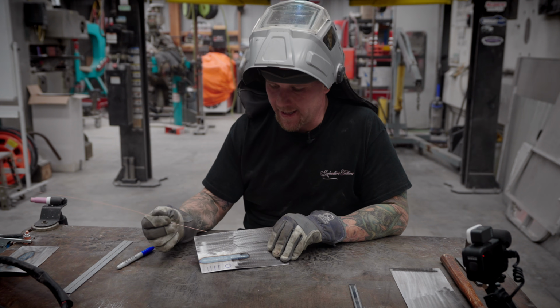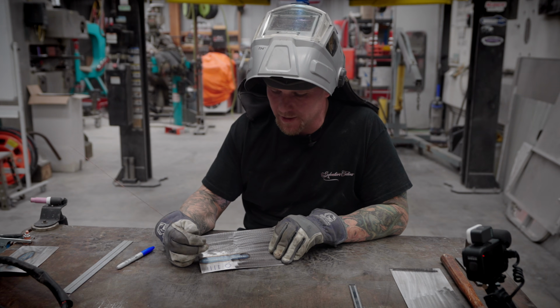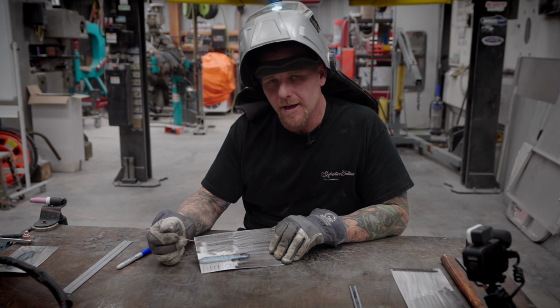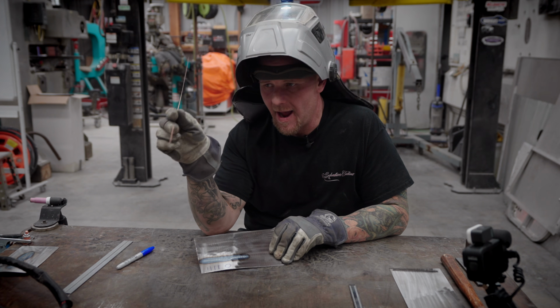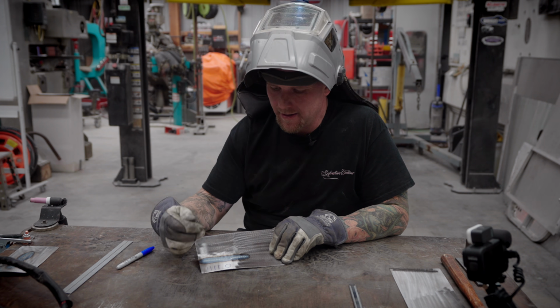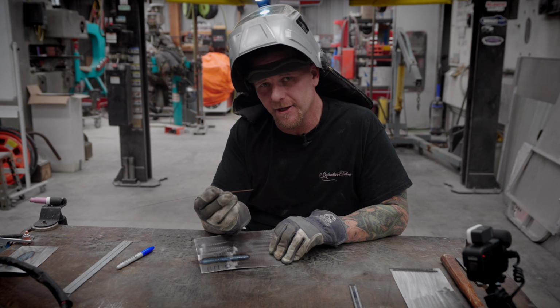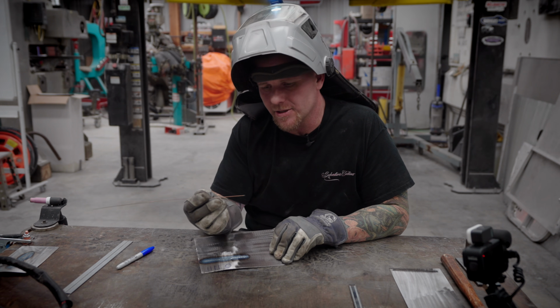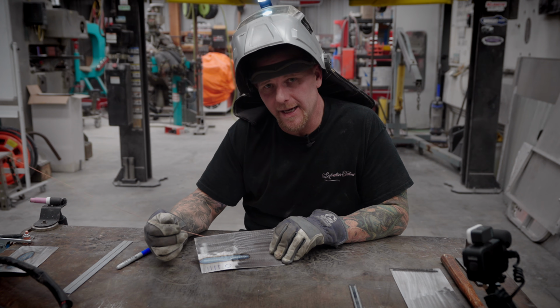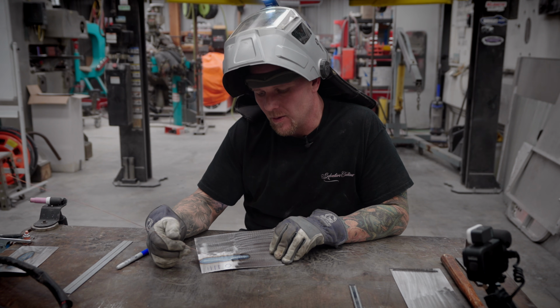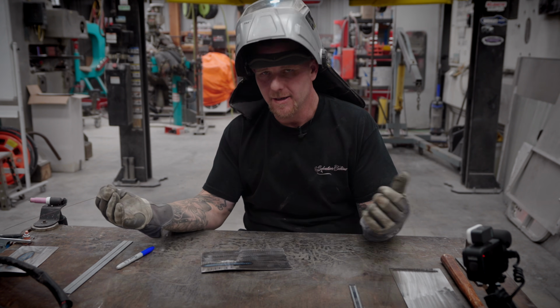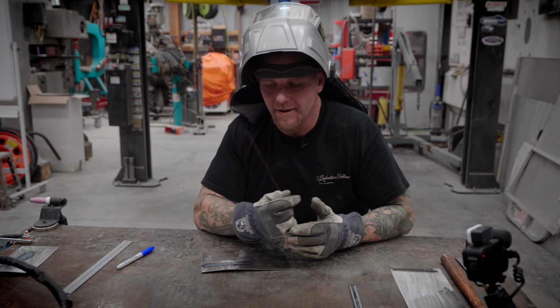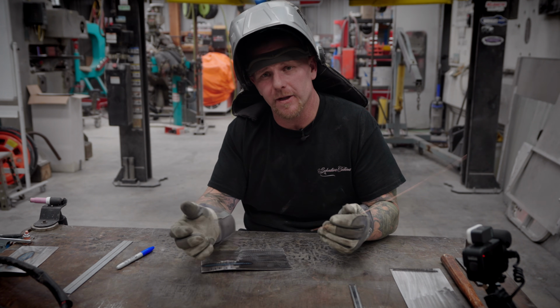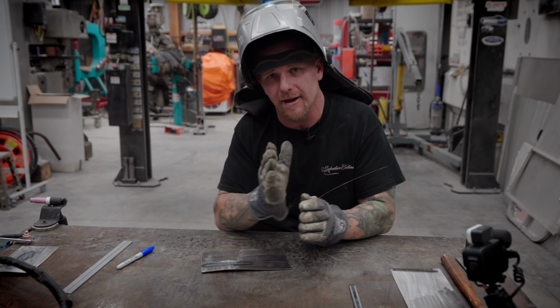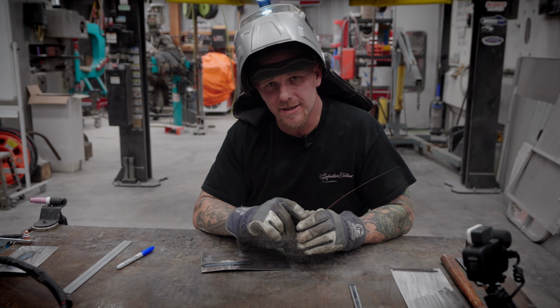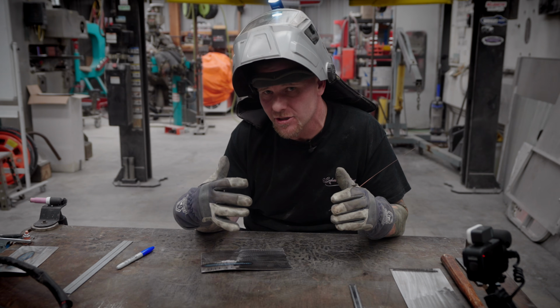When we're looking at the heat affected zone here, how one looks more consistent than the other, it all has a factor in how much travel speed, how much you're dipping the rod, because this filler rod is not heated, it's cold. And theoretically, if we break down what's happening with the weld, like why does it V out and sink down in the center? As we are adding the cold filler rod, it is shrinking into the center line of that weld. The heat affected zone is actually slightly stretched.